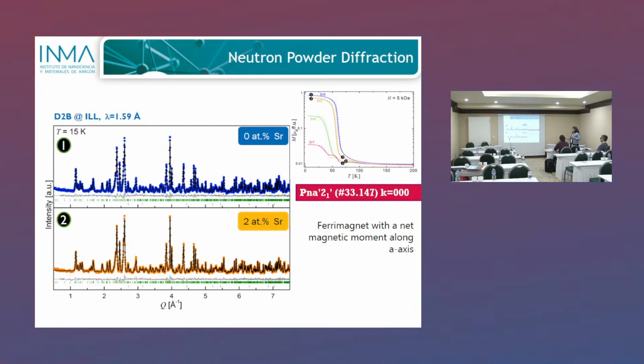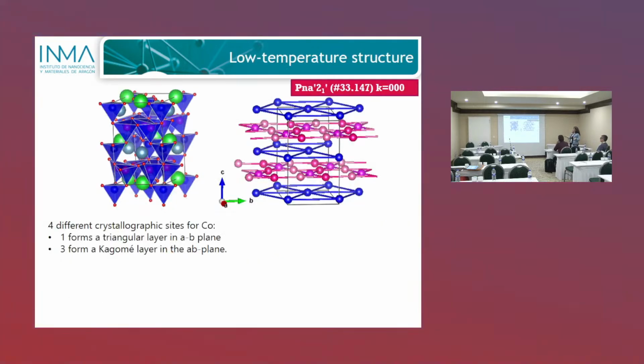And the system is indeed very magnetic, and it shows a net moment along the a-axis. If you do a plot of this structure, here you have the compound, and I've just removed all the atoms except cobalts, and I've put different colors for cobalts in a layer that is a triangular layer, and a pink layer that is a Kagome layer. But you shouldn't think of this as a layered structure, because actually they are coupled. And in the cell, there are 4 different cobalt sites crystallographically, different Wyckoff positions, let's say.